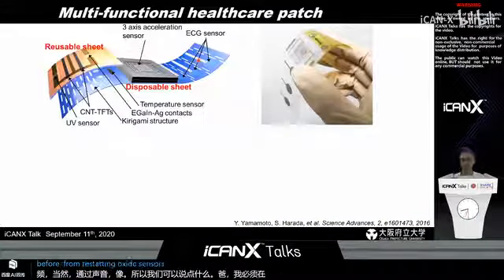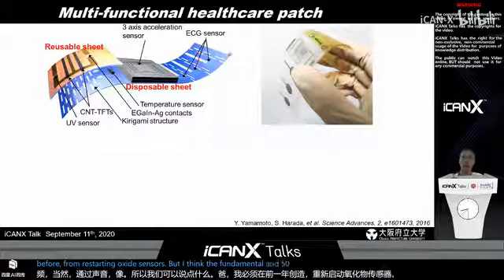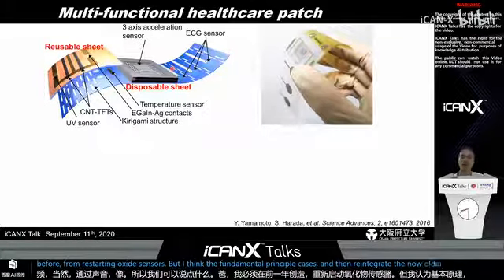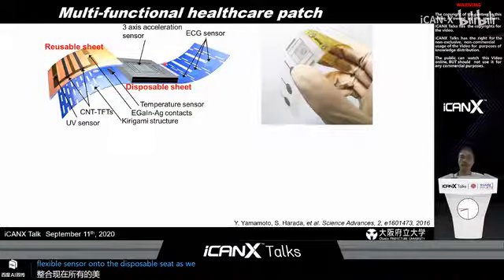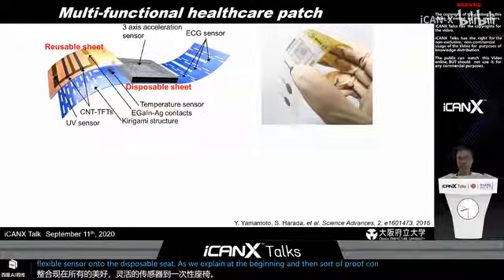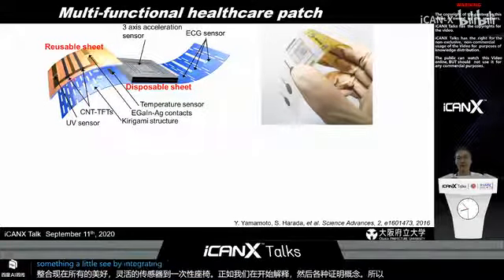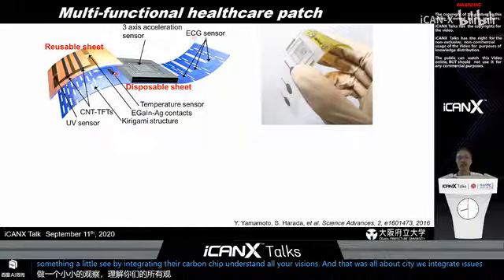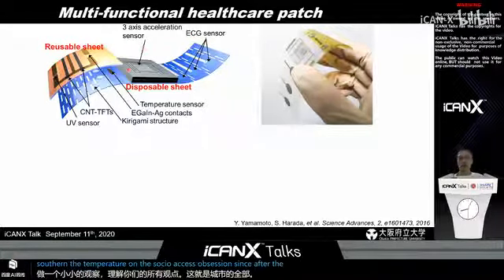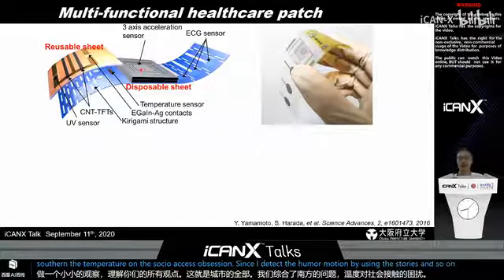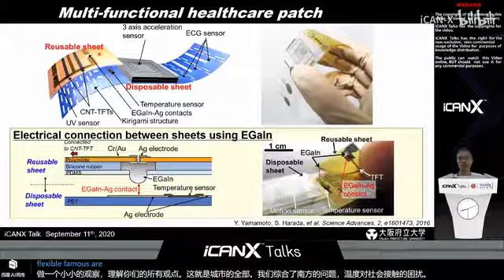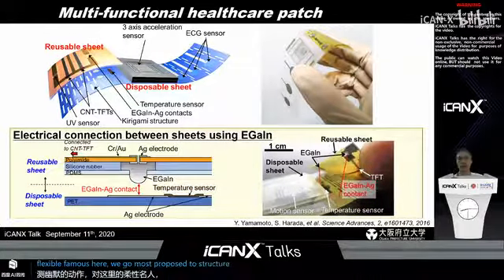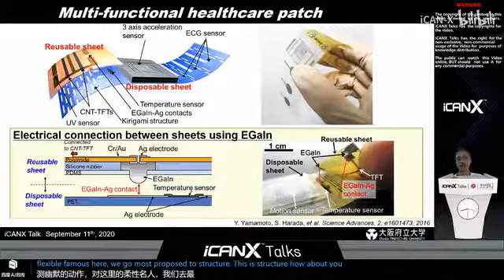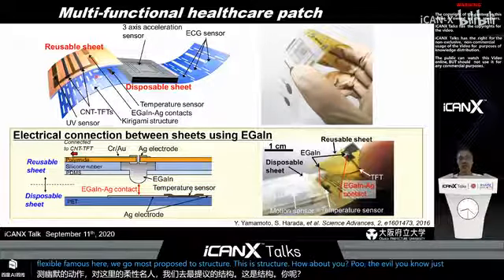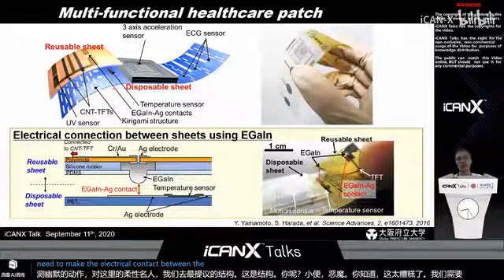Of course, by applying sunlight, we can calculate the UV power from this zinc oxide sensor. So that is our fundamental flexible sensors, and then we integrate all the printed flexible sensors onto the disposable sheet, as I explained at the beginning, as a proof of concept. We make a reusable sheet by integrating the carbon nanotube transistor and also the UV sensor. On the disposable sheet, we integrate the ECG sensor, the temperature sensor, and also a 3-axis acceleration sensor to detect human motion by using the strain sensor on the flexible films. Here we propose this two-sheet structure. However, even with a two-layer structure, we need to make an electrical contact between the reusable and disposable sheets.